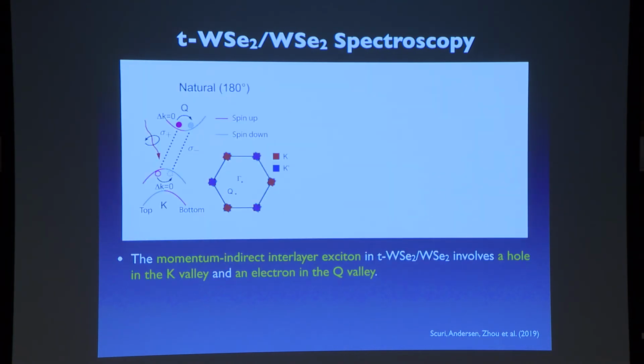Why? It can be understood rather simply. It turns out that in the case of so-called natural bilayers, because there is no twist angle, this is related to the so-called spin-valley degrees of freedom. The actual lattice looks like a hexagon, and as a consequence, the Brillouin zone also looks like a hexagon. And when you have natural bilayers where one layer is sitting directly on top of the other, then one layer's Brillouin zone is sitting directly on top of the other layer's Brillouin zone, which means that there is no momentum or energy mismatch between the two different valleys.